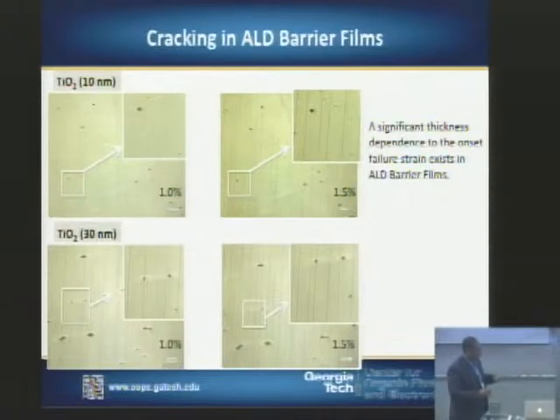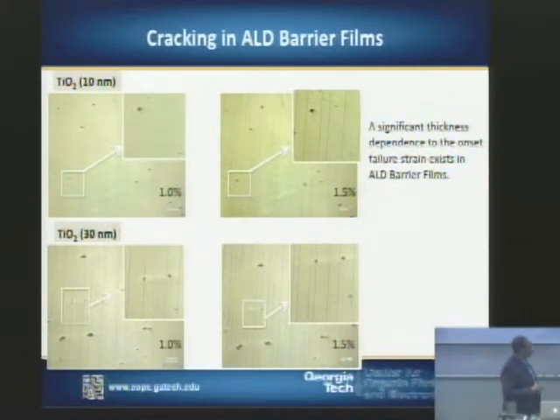So we want to look at further studies that we're currently doing right now, looking at how underlying films or surface treatments, pre-treatments, the smoothness of the film will impact this onset cracking strain in the films. But overall, we've looked at aluminum oxide as well as titanium oxide, and we see this particular effect. You see a shifting of the onset cracking strain with film thickness.